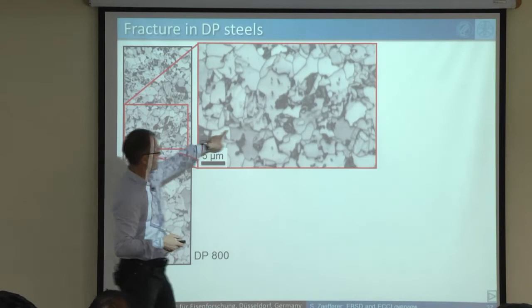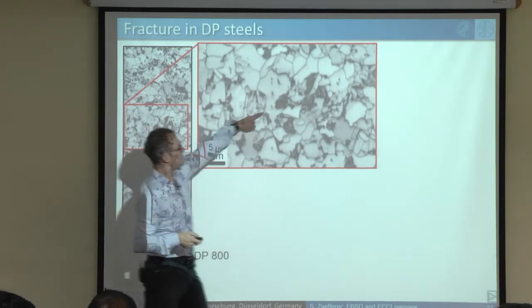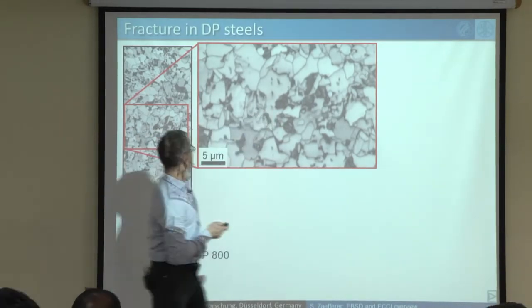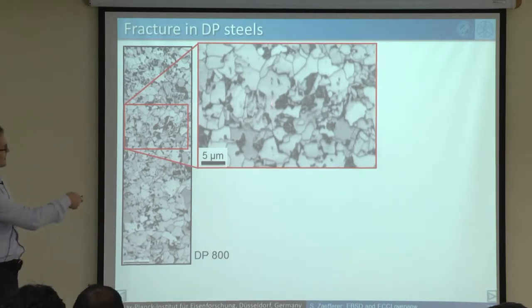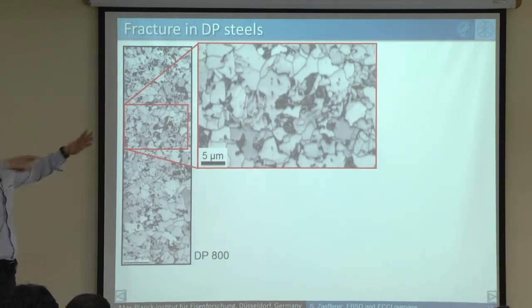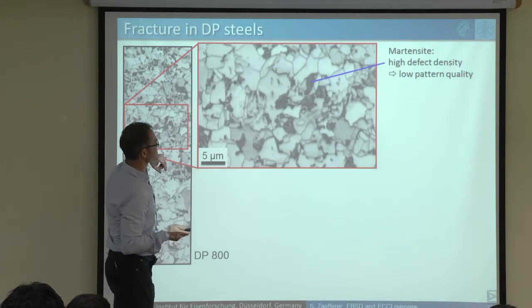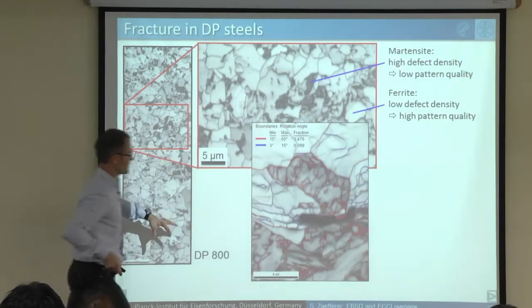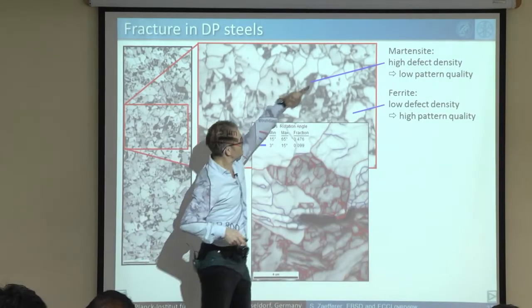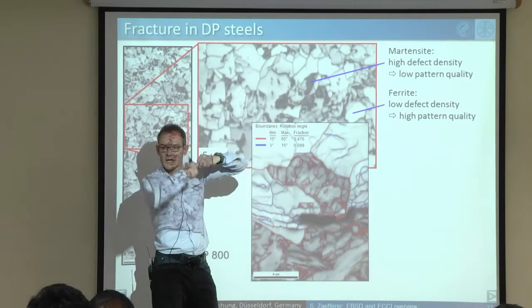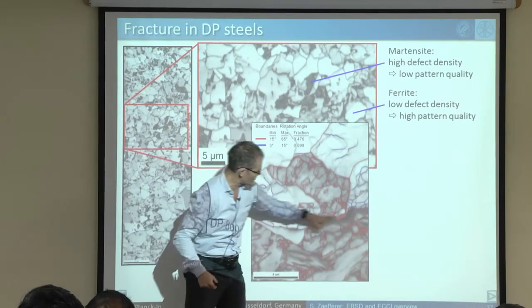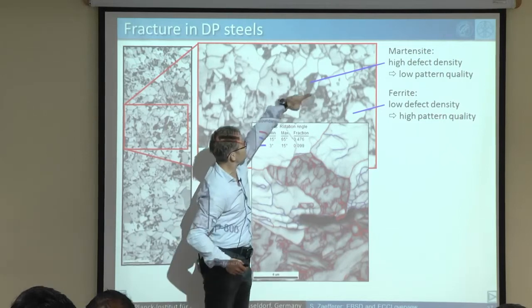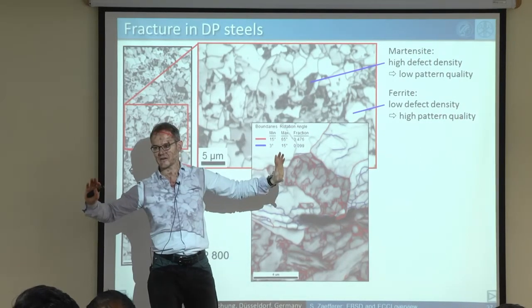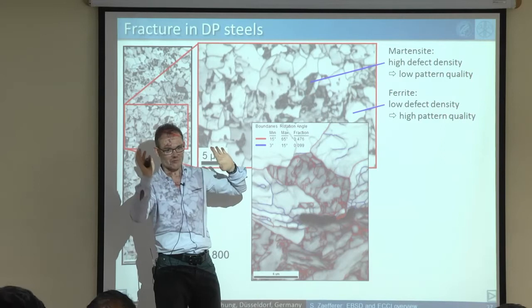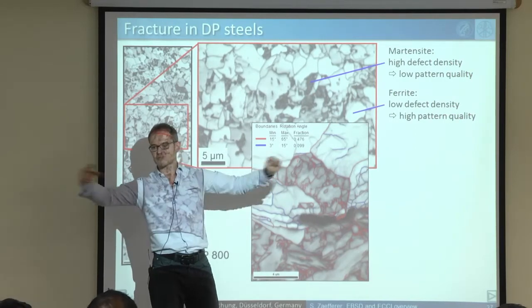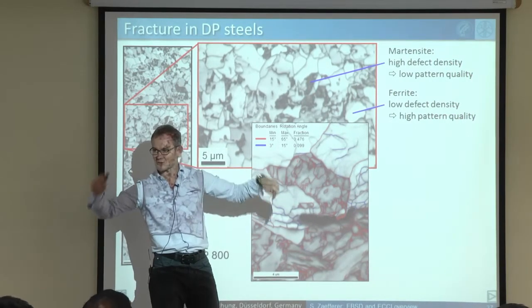Yes, of ferrite, these gray grains, and martensite grains. And we find islands of martensite in a matrix of ferrite. If you look into one of these martensite lamella a little bit more in detail, after a little strain experiment, you find it cracks inside of these martensite islands. The steel always cracks there, and it starts cracking already at 5% of strain. It still supports then straining until 30%.